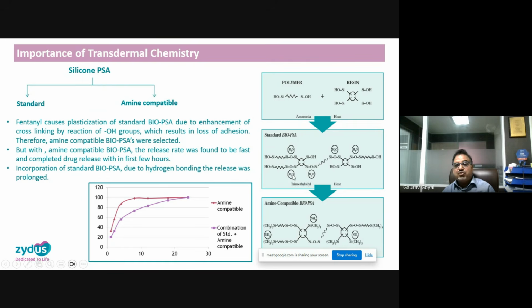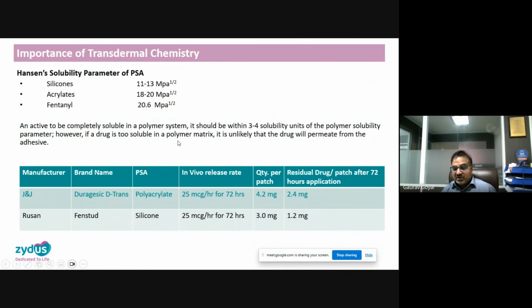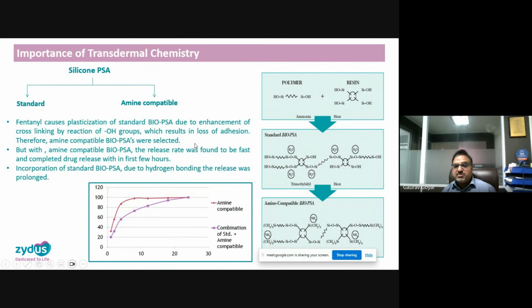But what is the different problem with this? It has very good solubility in the standard bio-PSA, but it reacts with the drug molecule, and the drug release is very retarded. So we used amine compatible, where the hydroxyl group is not there, and the drug release is very fast. In fact, drug release is very fast because there is no hydrogen bonding between the fentanyl and bio-PSA. And moreover, as I told you, there is a problem of crystallization because the solubility of fentanyl is low inside the silicones, as far as the Hansen solubility parameter, which we have seen in the previous slide. To make it soluble, we used a standard polymer because of the hydrogen bonding; the solubility of fentanyl is increased in the bio-PSA.